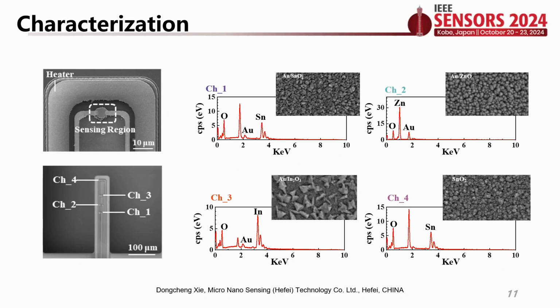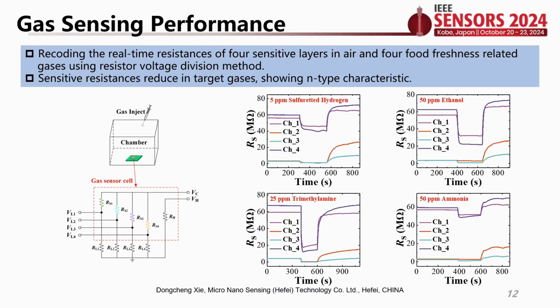The characterization of the cantilever sensor cell and the sensitive material are shown on this page, including the top view of the cantilever, the detail of one sensing region, and morphology and EDS images of the sputtered materials. The left part of this page is the setup for the gas sensing experiment. The sensor cell was placed in a well-closed chamber, and the target gas was injected into the chamber to form an environment with specific gas concentration. After that, we open the chamber and allow the gas to freely diffuse.